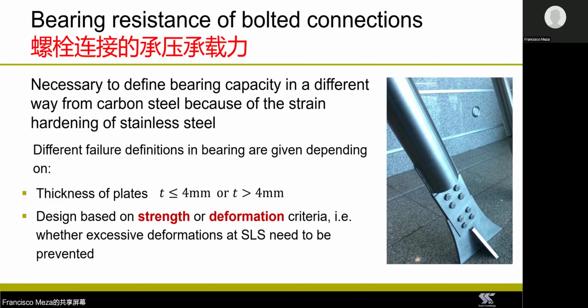Now, the bearing resistance equations for stainless steel also take into consideration whether the deformation at the bolt hole needs to be limited or not. So for the case in which deformation is a design consideration, the equations that Eurocode 3 Part 1.4 gives were derived by targeting a 1 millimeter deformation at the bolt hole under service loads. But if deformation is not a design consideration, Eurocode 3 Part 1.4 allows the use of different bearing resistance equations that will predict greater resistances.